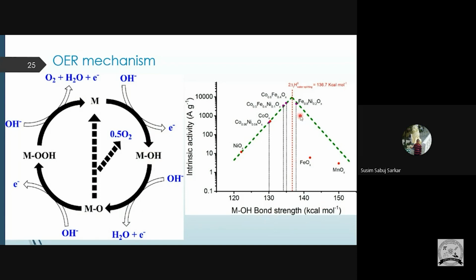So here also you can see that in an optimal case, with the change of the MOH bond strength, we can get a volcano plot. We have to choose the transition metals in such a way that the bond strength of the MO is not very loose and not very high. If the MOH bond strength is very high, the reaction can't proceed, because it can't break and give the free metal. And if it is very loose, it can't form the MOH bond. So we need an optimal bond strength.